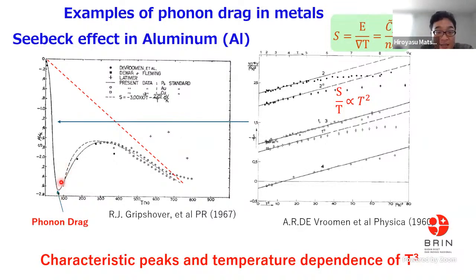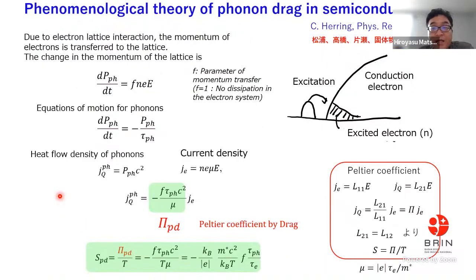So the characteristic temperature is around 50 kelvins, so very, very low temperature. This is a characteristic feature of phonon drag. So in the semiconductor case, we can get these equations. I skipped the details, so if you would like to know the details, please ask after this seminar. Anyway, the Seebeck coefficient in the semiconductor case is proportional to this equation, tau phonon.